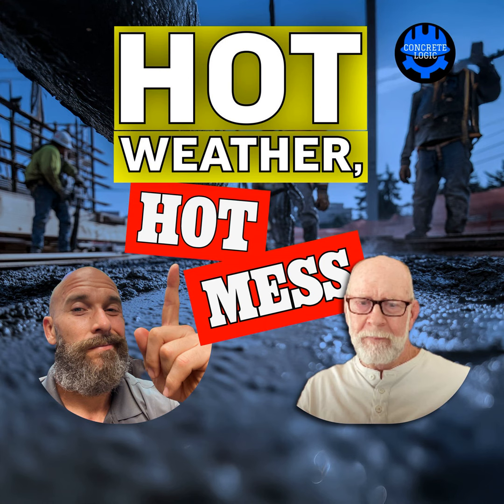In field concrete, which even this graphic doesn't consider, it's way worse than what we're reading here, because nothing's going to stay at 100% relative humidity, and it's not going to stay at 73 degrees. It's going to get hot, it's going to get cold, and those changes are going to cause movement. So you're getting washout and scrubbing, and all kinds of things going on in the top surface of the concrete. If we control the top surface of the concrete, the durability issues will go away. But we're not doing that.